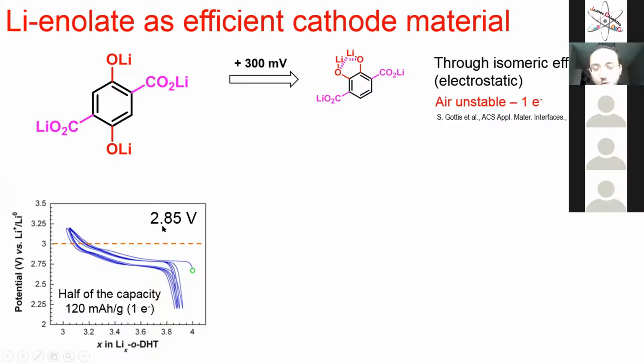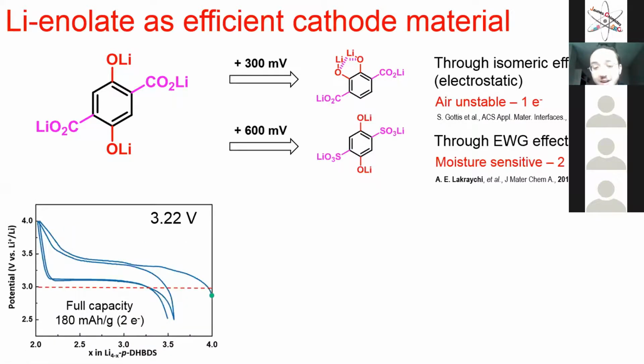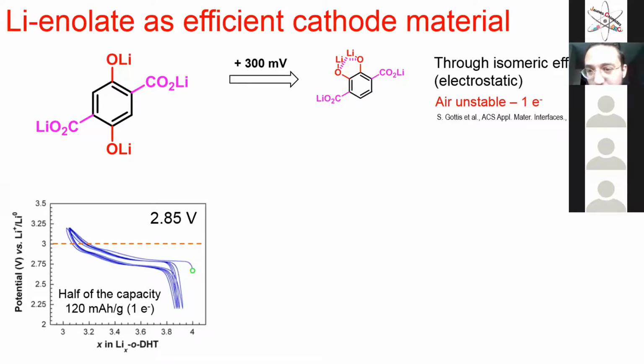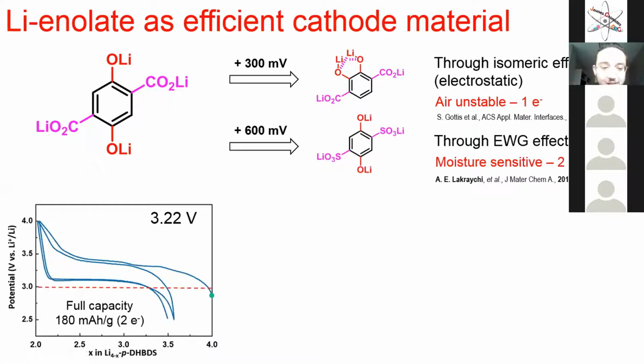So here you have 2.85 volt, but it is still not enough, because this is lower than 2.91, and this one is not stable in air. Then you can replace the carboxylate with another electron-withdrawing group. Here we have tried the sulfonate, and as you can see, we can produce a higher potential. Here you have the line of 3 volt, and this one reacts above it. That's why this molecule is stable, not in air, but in oxygen, because it doesn't react with oxygen, but it is unstable to moisture. It takes some water from humidity, and then you will have a worse performance. You still need to process this molecule in a dry room.